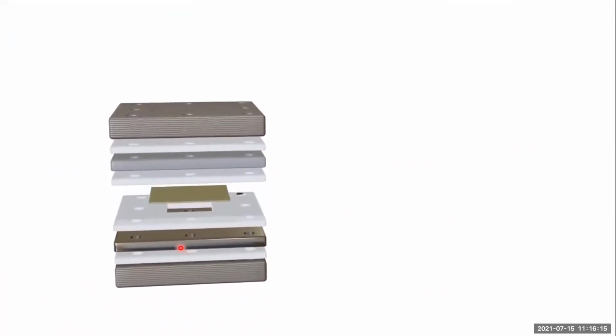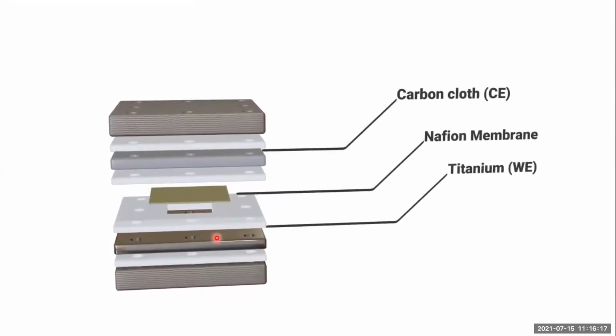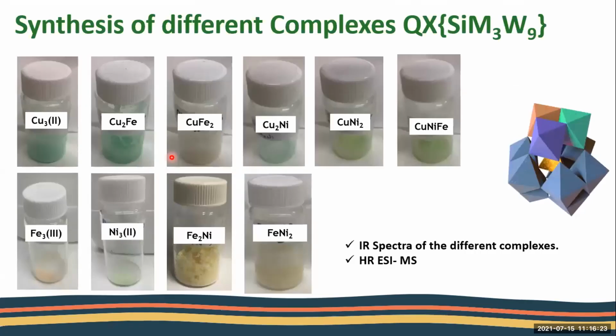The first electrode is a titanium electrode as the working electrode, and the second electrode is carbon cloth as the counter electrode. So we succeeded in synthesizing all the catalysts with all the combinations of copper, nickel, and iron. And in order to be sure that we did that in the right way, we characterized them by 2 methods. The first method was IR, and the second was high resolution MS.